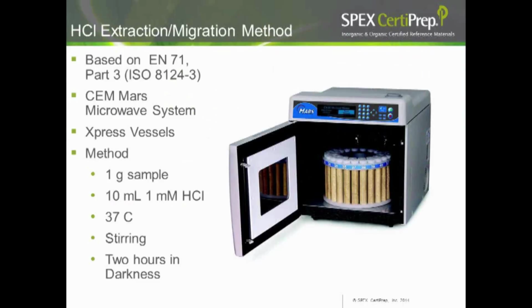For this study, we based it on the EN71 migration extraction method. We did use our CEM Mars microwave system again with our Xpress vessels. 1 gram of sample and 10 mL of 1 millimolar HCl to simulate a gastric fluid environment in a child's stomach. It was run at 37 degrees with stirring for 2 hours in darkness.